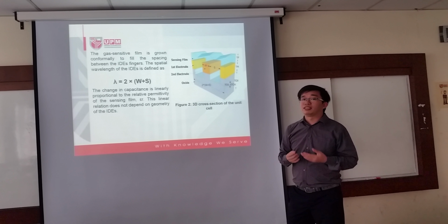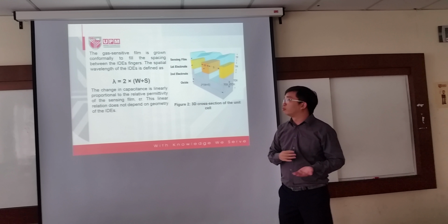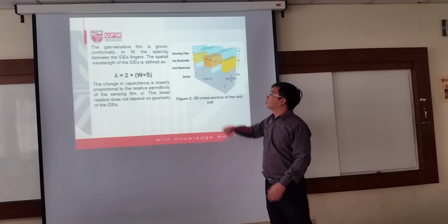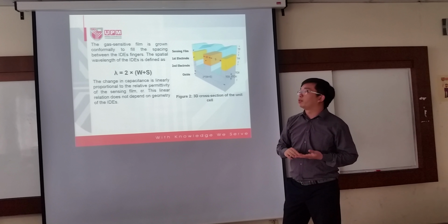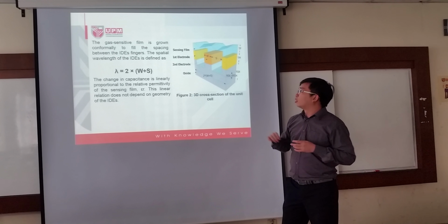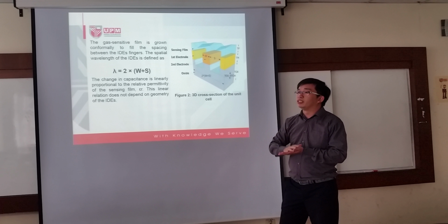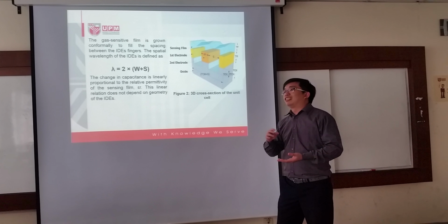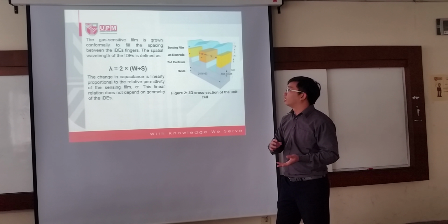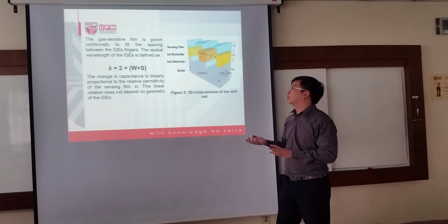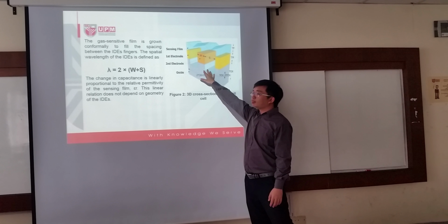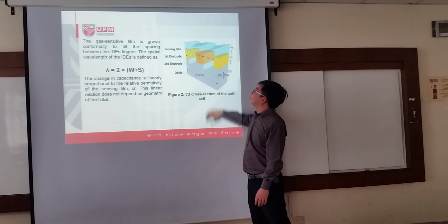And the change in capacitance is linearly proportional to the relative permittivity of the sensing film. This linear relation does not depend on the geometry of the IDEs. So any change in the relative permittivity due to the gas sensed by this sensor will cause the capacitance to change. And this relation does not depend on the geometry of the IDEs, which is the width and the spacing here.